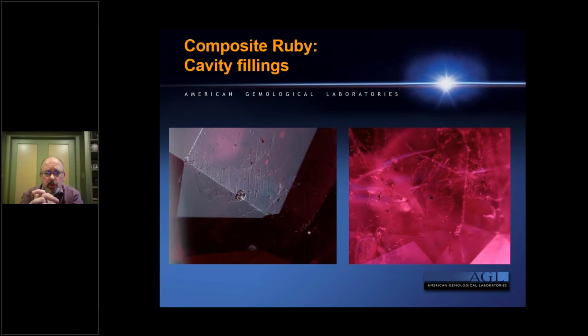This image actually demonstrates for me how impressive this treatment can be at times. This glass is so efficient and so effective. In the left-hand image, this was hard to actually capture because the RI match of the lead glass and the corundum is virtually identical. There's no luster difference you see here. What helped me to recognize it was the fact that the glass is softer than the corundum. So you have polishing lines which are coming in, and this is the boundary of where the cavity is, and all of this interior is a high lead content glass. Now, when I took off the overhead light and I just used the dark field illumination, that's what you see on the right.